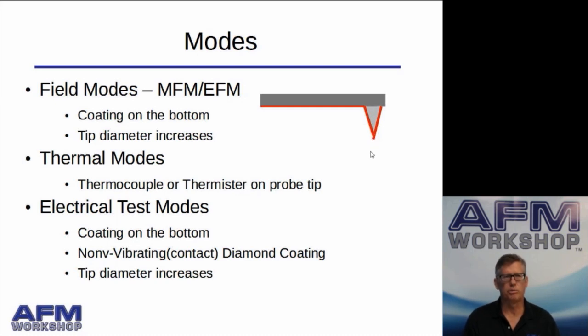So if you start out with a probe that has a diameter of, say, 30 nanometers, and you put a 50 nanometer coating on it, the diameter of the probe gets much larger. Therefore, for a lot of these field modes, the ultimate resolutions are not as good as they would be with a standard topography measurement with an AFM.